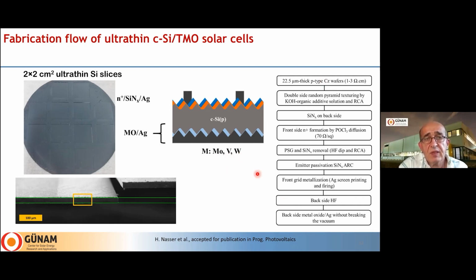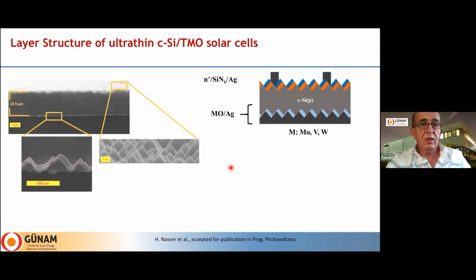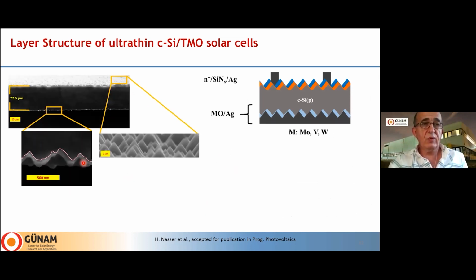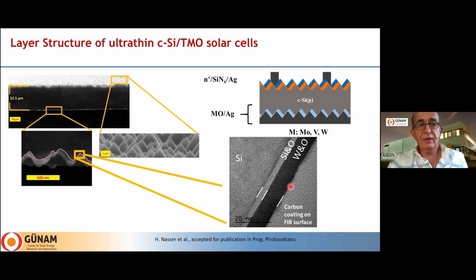So the rest of the fabrication steps are standard silicon solar cell fabrication steps. We have, again, N-type doping on the front side and P-type silicon as an absorber. On the back side, we have only these materials. And again, there is no doping. If you look at the structures more closely, you see we were able to get a conformal coating on the front side, and also on the back side. Sorry, this one is the back side pictures. This is a high resolution TEM image of the same region. So the metal oxide layer is nicely seen here with very sharp interfaces, and there is a silicon oxide layer formation between silicon and tungsten oxide layer, as you see.